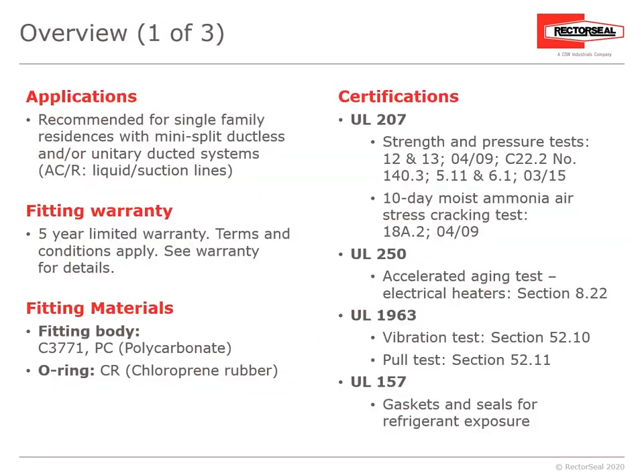Now an overview, the applications. The ProFit Quick Connect is recommended for the single-family residences with ductless mini splits or unitary ductless systems. The warranty on the fittings, it's a 5-year limited warranty. The fitting materials. Again, the fitting body is a polycarbonate brass body. The O-ring is a chloroprene rubber elastomer. That's what makes the O-rings impervious to any kind of leakage or breakdown when exposed to the POE oil and those refrigerants. And then the certifications, we have the UL 207, the strength and pressure test, UL 250, accelerated aging test, UL 1963, the vibration test, as well as the tensile or pull test, and then the UL 157, the gaskets and seals for the refrigerant exposure.